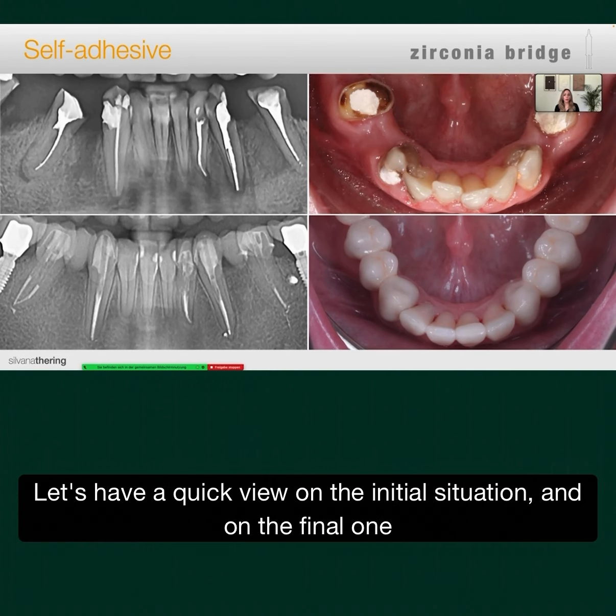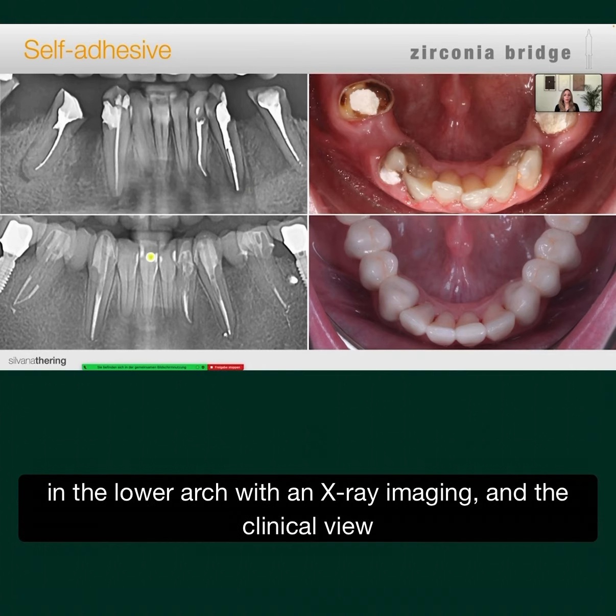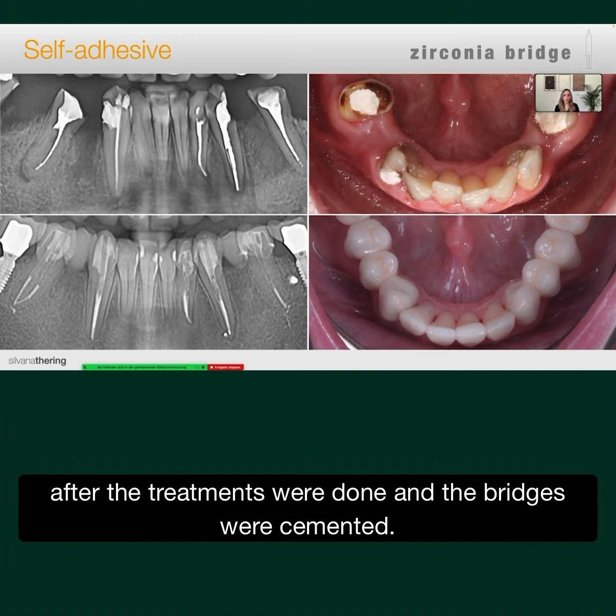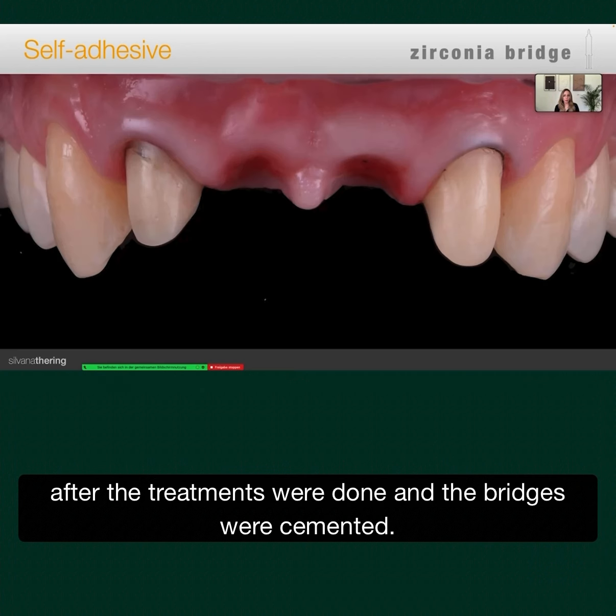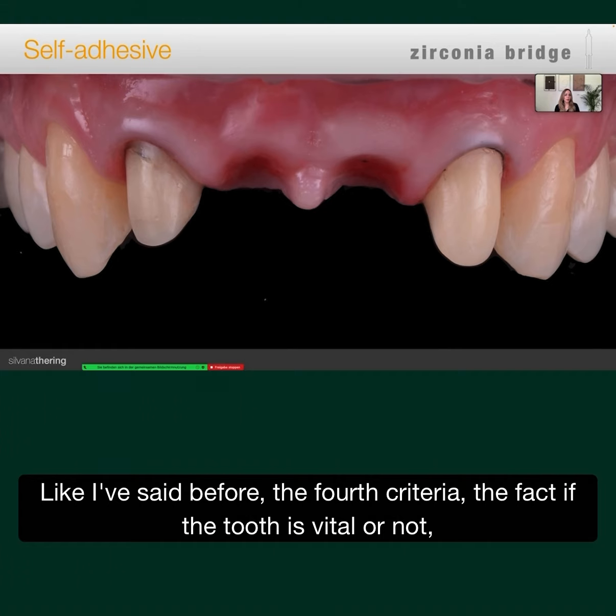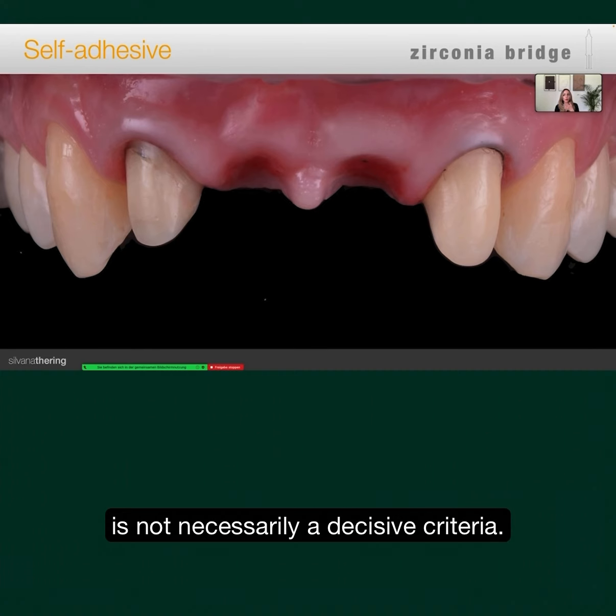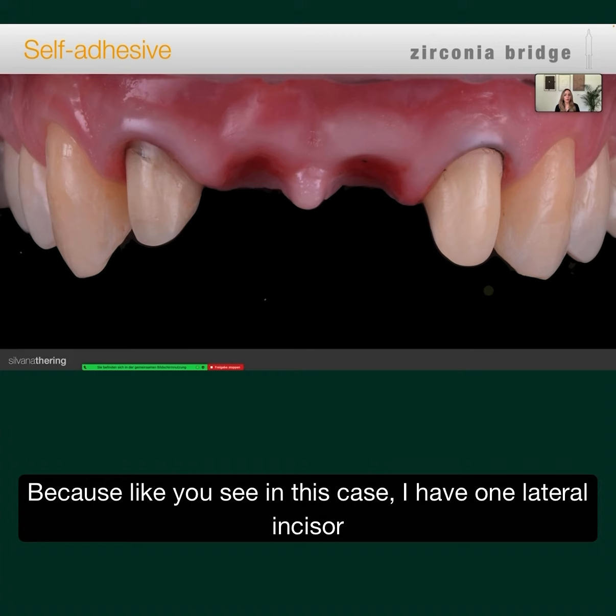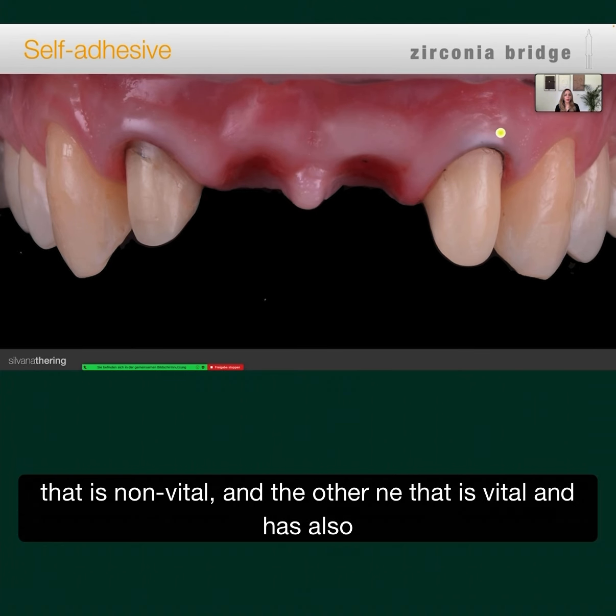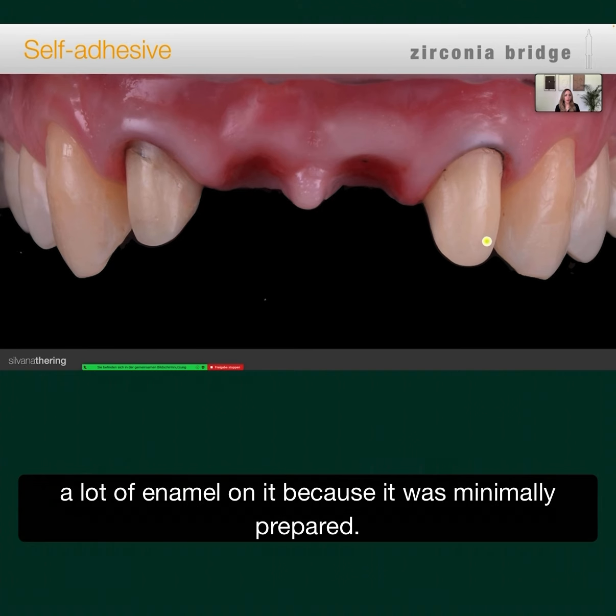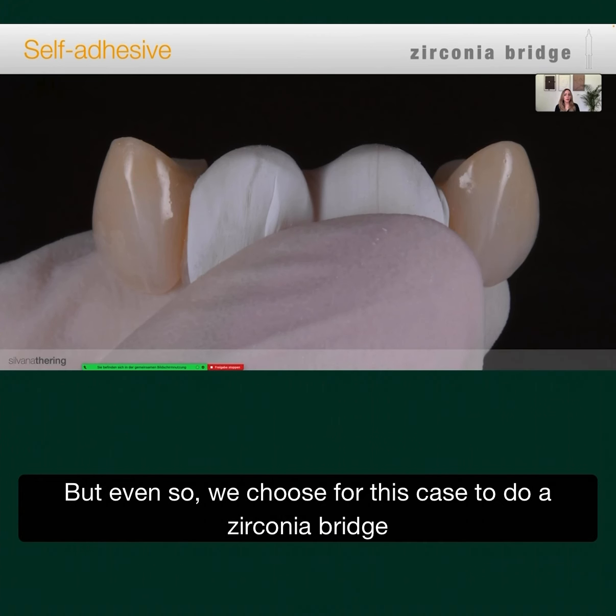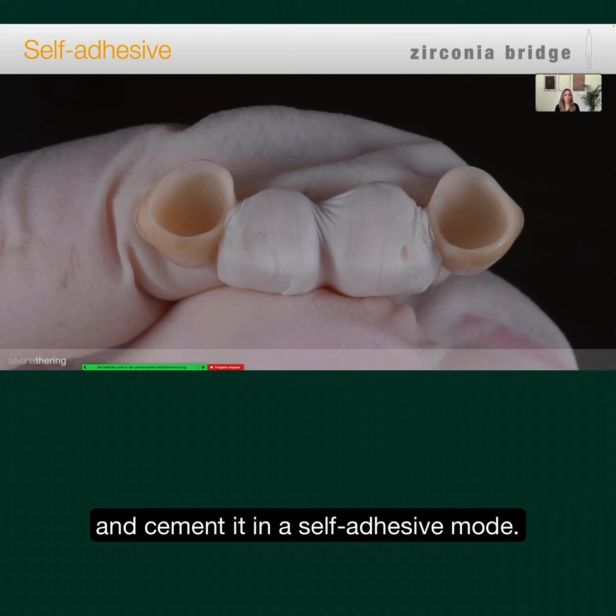So let's have a quick view on the initial situation and on the final one in the lower row, with an X-ray imaging and a clinical view after the treatments were done and the bridges were cemented. Like I've said before, the fourth criteria, the fact that the tooth is vital or not, is not necessarily a decisive criteria, because like you see in this case, I have one lateral incisor that is non-vital and the other one that is vital and has also a lot of enamel on it because it was minimally prepared. But even so, we chose for this case to do a zirconia bridge and cement it in a self-adhesive mode.